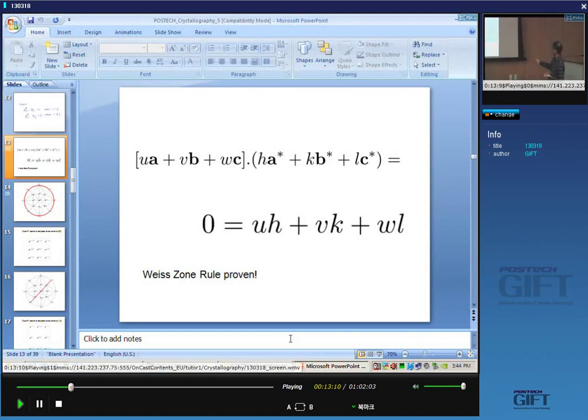Zero, because B star is at 90 degrees to A, and therefore that product is zero, and similarly this product is zero, so we recover only the term uh when we do a dot product with uA. Similarly, vB dot kB star will be vk, but all other products will be zero, and so on. So we've proven the Weiss zone rule, and I haven't defined the vectors A, B, or C. They could be anything pointing in any